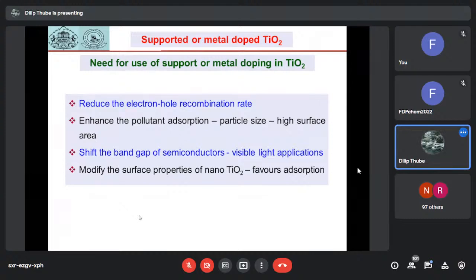So, what is the need for use of support or dopant in the TiO2 nanoparticles? Because nano TiO2 or the nascent TiO2 particles have a high electron hole recombination rate, and the band gap is very high. Therefore, if you make use of a support or a metal dopant, the dopant material or support material may have an intermediate level between the valence band and the conduction band, and therefore the energy gap will be reduced, the band gap will be minimized, therefore the electron hole recombination rate can be minimized, and therefore the electrons will be made available as well as protons or holes are also made available for reduction as well as oxidation technology respectively.